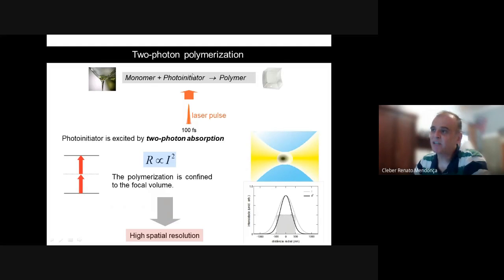We add a photoinitiator, which is a small molecule that will be excited by our femtosecond laser light. It will be excited by two-photon absorption. And this photoinitiator plus the monomer will start the polymerization reaction. So in the end of the day, I go from this viscous liquid to a solid piece of plastic, which is induced by two-photon absorption.